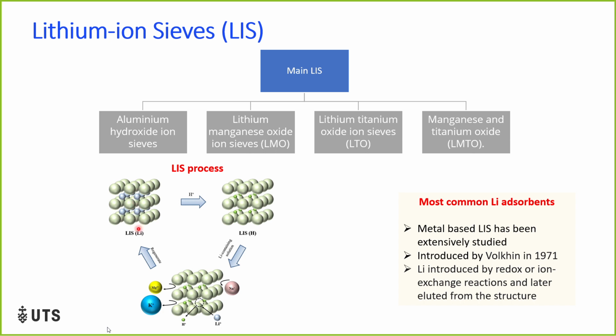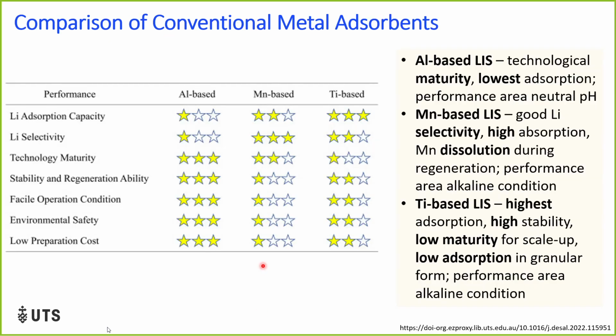So if you see the lithium ion selective structure, the hydrogen can be replaced with lithium, and lithium can also be replaced with hydrogen. So in your lithium ion selective adsorbent, you can simply exchange your hydrogen with lithium so that you can have a higher concentration of lithium from this lithium ion selective adsorbent.